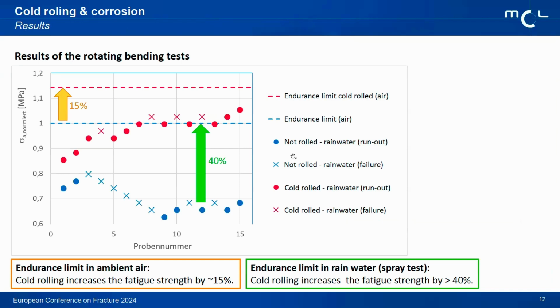Okay, then to the results. First, we should compare the dashed lines again. So the endurance limit in air is the blue dashed line, and that's for the standard specimen, not rolled. Afterwards, due to the cold rolling, the red dashed line, you can see we increased the fatigue strength by approximately 15%.